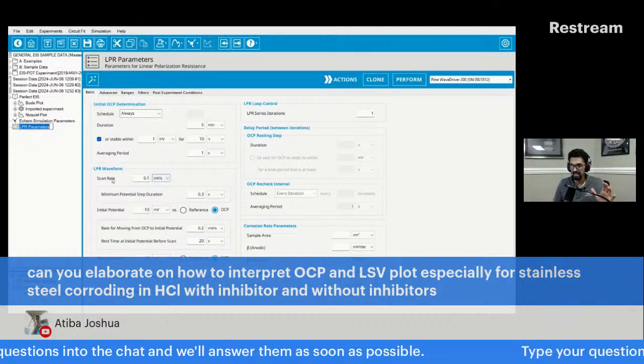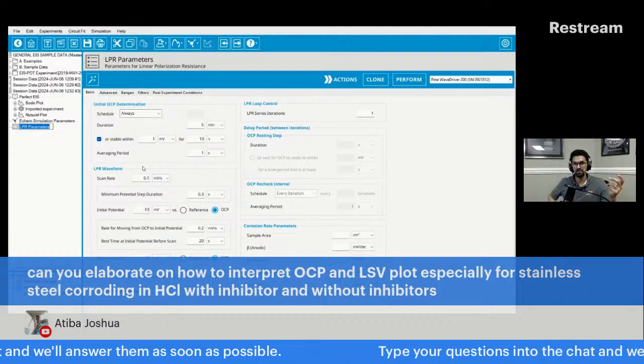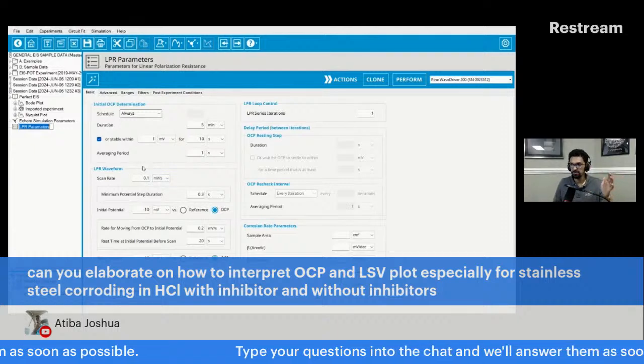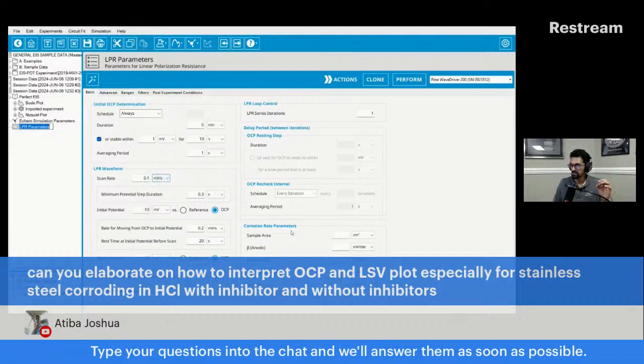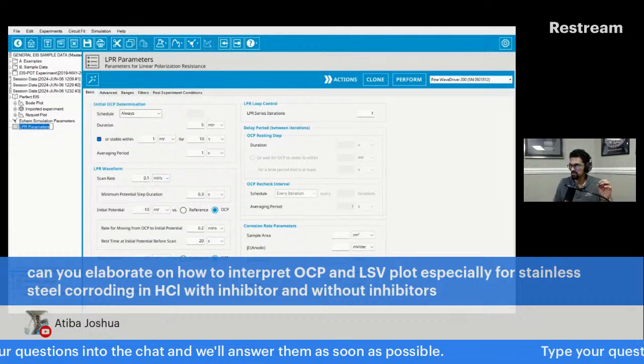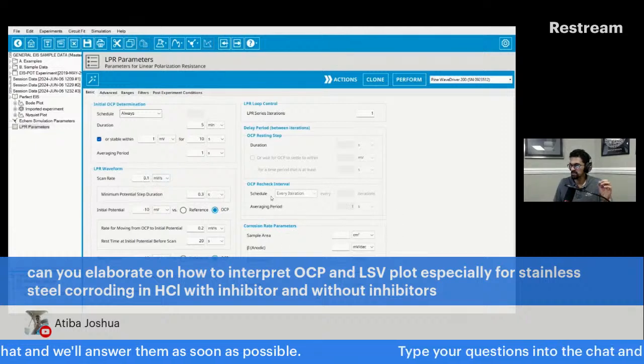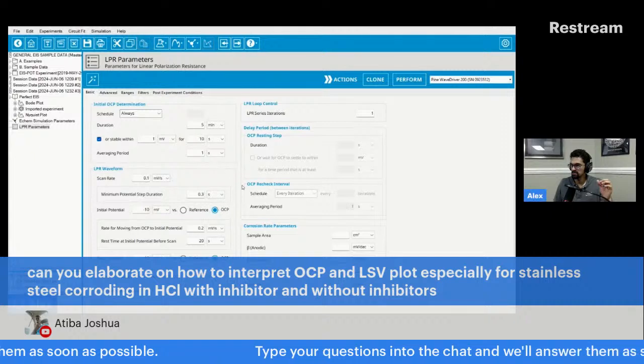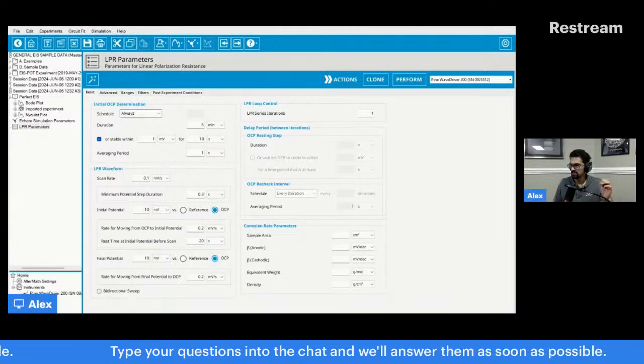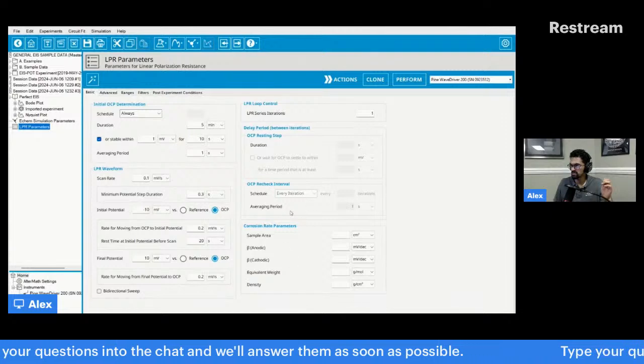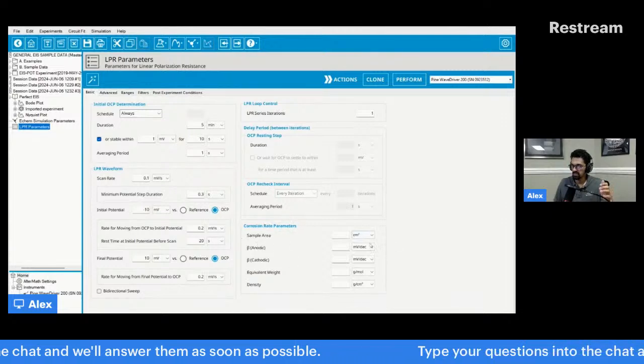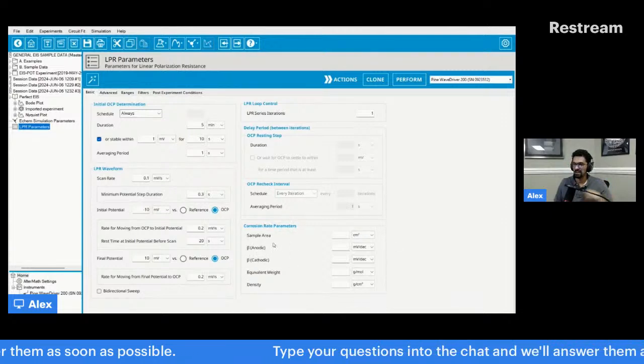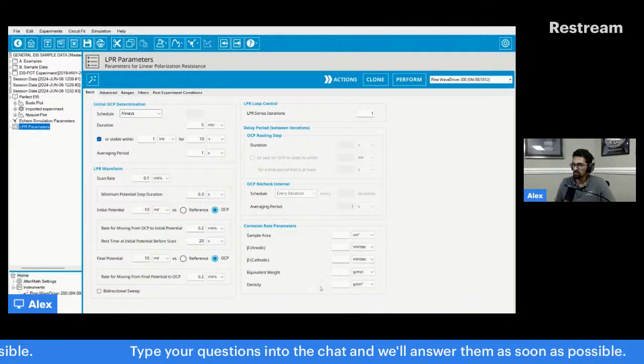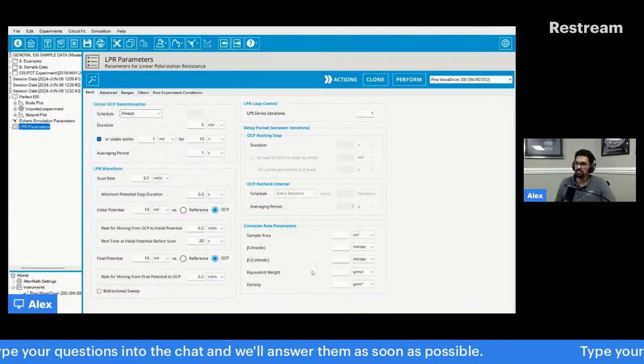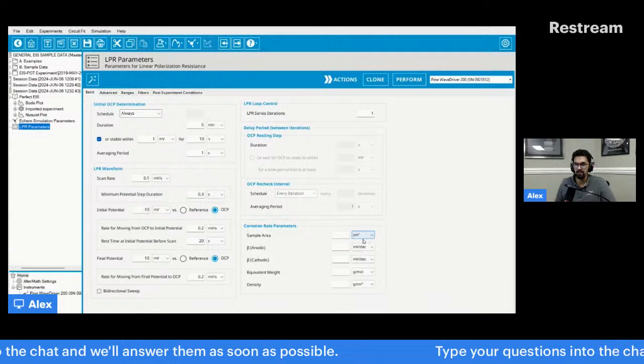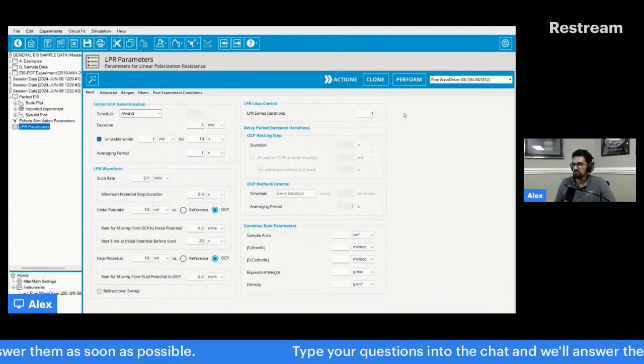And then the LPR waveform is actually a very slow LSV. But then you usually need some of these other corrosion parameters, and I hope that this is visible. It's not very visible. Let me hide this. So these other corrosion parameters that are a little bit hard to see: the corrosion rate parameters, sample area, the anodic and cathodic beta constants, equivalent weight, density. These are all things that people use when doing LPR. And they'll do numerous LPRs.